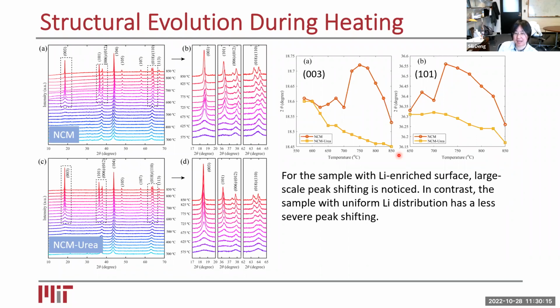The take-home message is that if we have this lithium enriched surface, then the sample will be very, very sensitive to the annealing conditions. You cannot have too low a temperature, you cannot have too high a temperature. But in the second case, where we add urea, the end product is less sensitive in its peak, meaning that it can withstand a relatively wider range of temperature. So it gave us hope that we could try a high temperature annealing.